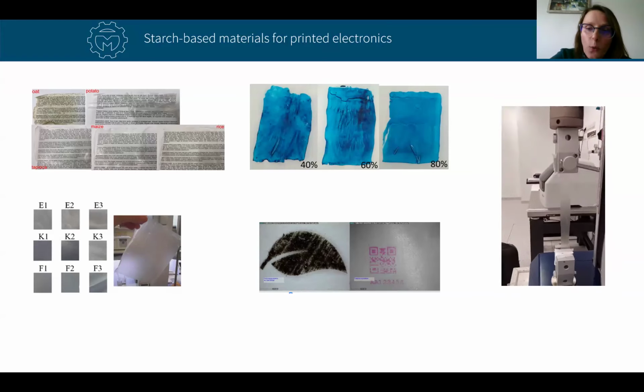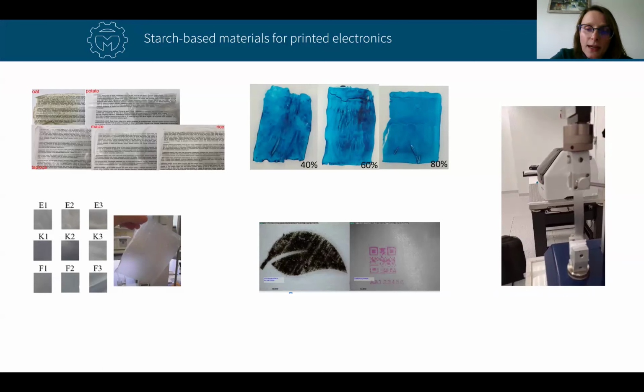For example, we have obtained films with good quality, with quite a long lifetime, and even after a few years of storage, they still have acceptable properties. The only thing that changed was the color. The old ones are more yellowish than the fresh ones. But also at the same time, they have suitable elasticity, about 20%, which might be valuable, for example, for flexible electronics applications when we use those materials for e-skin electronics or some devices.